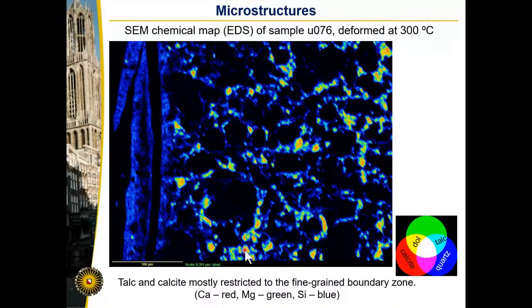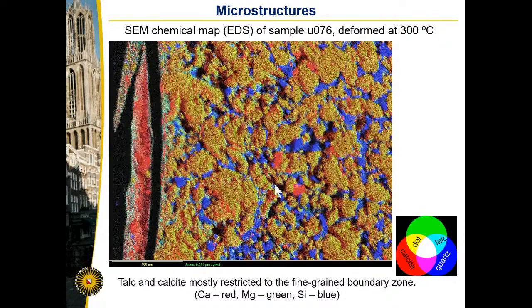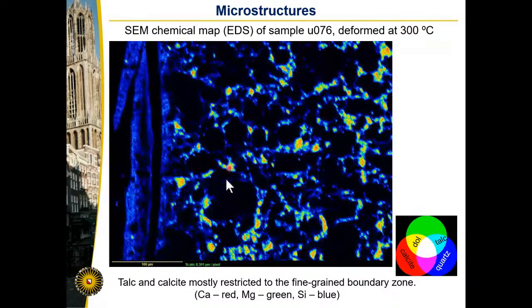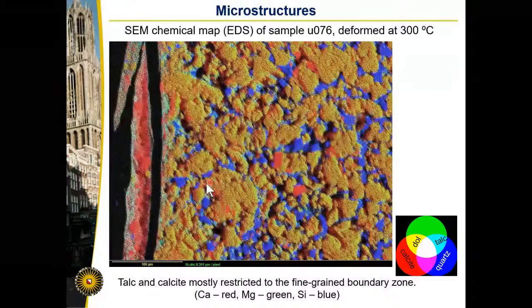We can see this more clearly if we only look at silica. So this is a 16 color lookup table. The quartz grains show up as very bright spots, and in between you can see that wherever you have silica, it must be a silicate phase, so not dolomite and not calcite. You can see clearly that it is present in this boundary shear, but also in between the dolomite grains, and along the grain contacts, like here, you can see that talc is being formed.